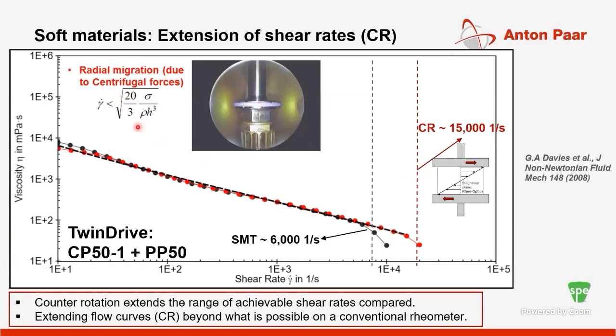Typically for Newtonian materials, there are equations which can predict at what shear rate this would happen. This would typically depend on the surface tension, the density of the material, and the height or gap you're using in the system. Here I'm showing you some data on a cosmetic cream which I characterized.